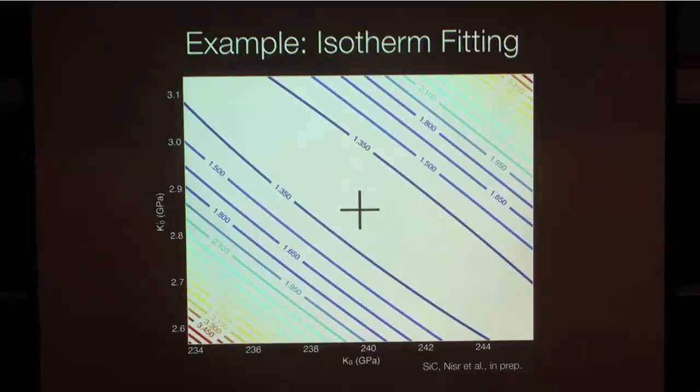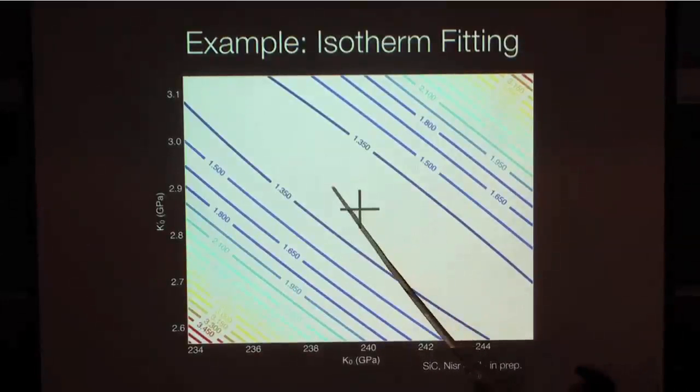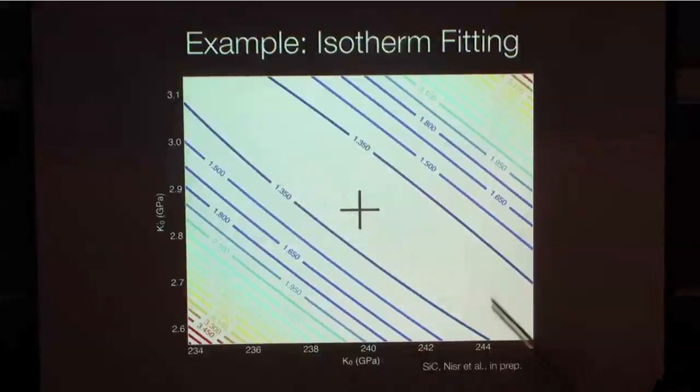So in normal regression, you run the regression until you get the lowest possible chi-square, right? If you look at the contour, yes, it's decreasing toward this direction, but what do you learn from this diagram? K0 and K prime are related to each other. They are negatively correlated. So the fact of the matter is, any pair of values you take along this line will be equally okay.